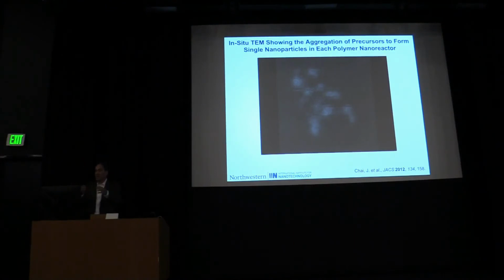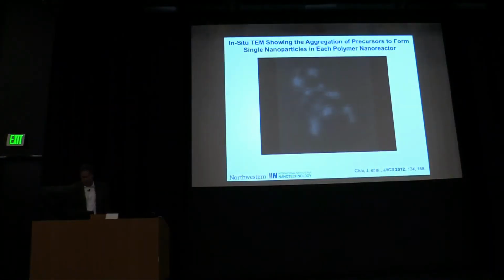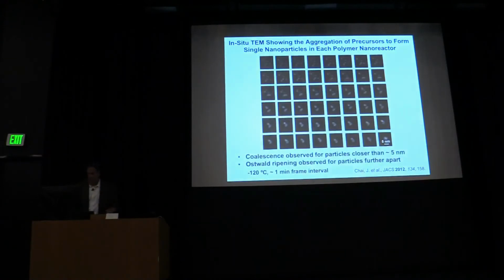Because when you put an electron beam and kind of treat that as a reactor, it's an interesting reactor where all the reactants are going to go into forming one product. And I can map that process as a function of temperature of the electron beam. So I'm going to show you the birth, growth, and ultimate life of a gold nanoparticle. And you can watch the process take place. The nuclei form, they begin to merge, coalescence takes place, and at the end of the movie you see the one nanocluster that forms. That's kind of a neat movie, but there's information there. I can take that down and look at the different frames, frame by frame, going from nucleation and growth all the way to final coalescence.